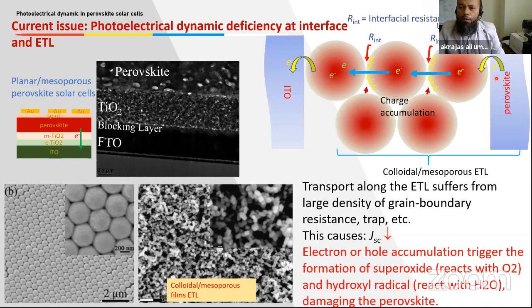This is the perovskite. This is the ETL of TiO2. The nature of charge transfer from perovskite to particle is also influenced by the nature of coupling here. And when an electron is already injected into the material, depending on the coupling between adjacent particles, some of them can successfully transport to the external circuit, but actually most of them accumulate at this interface.